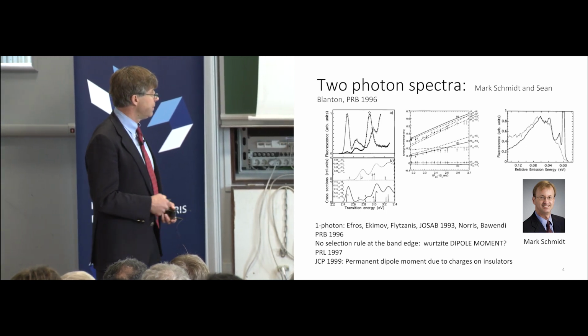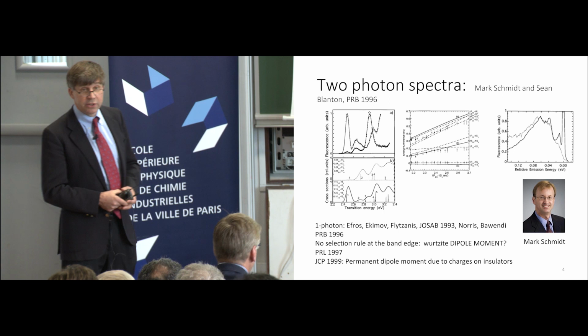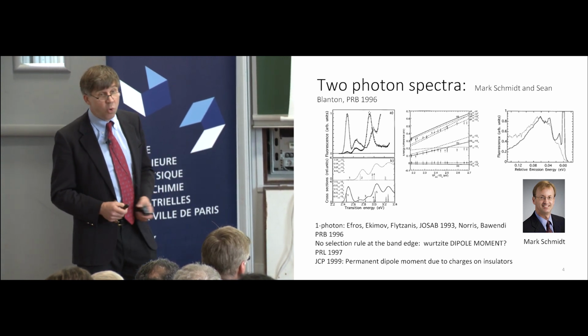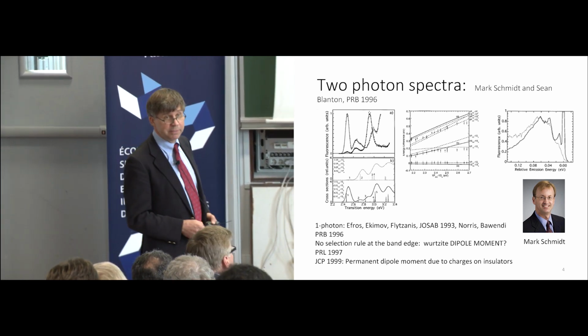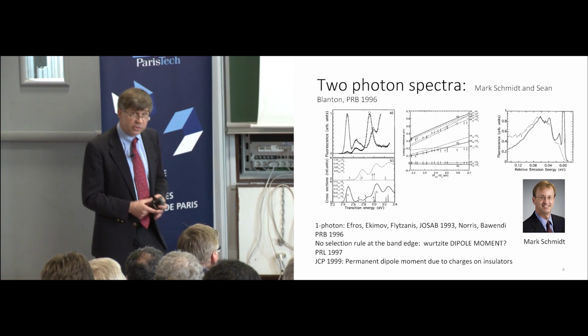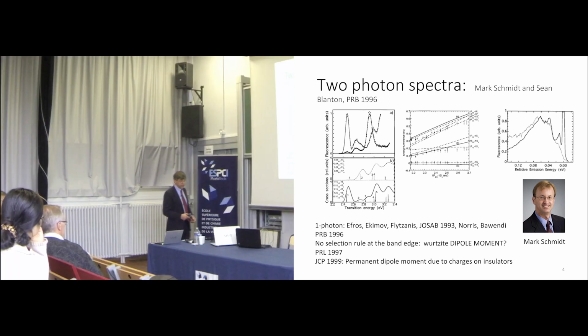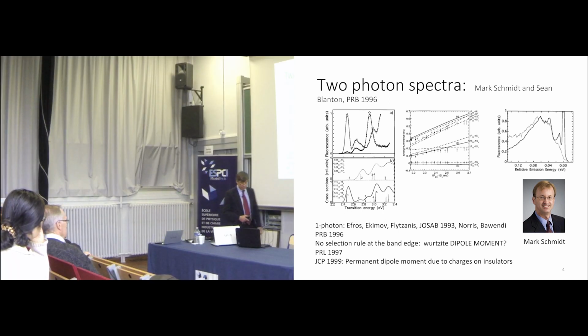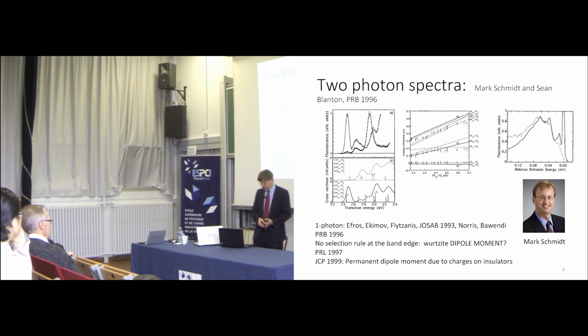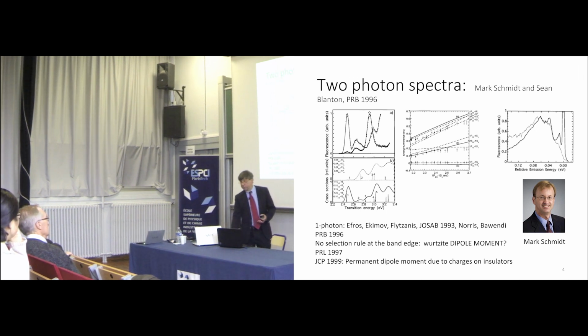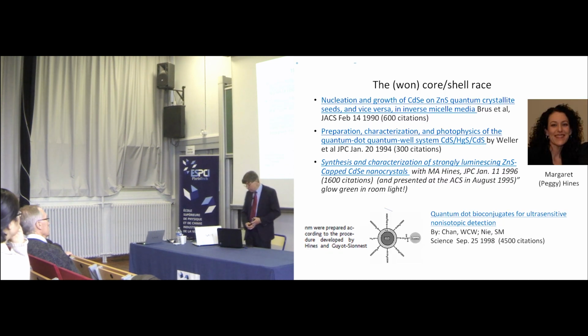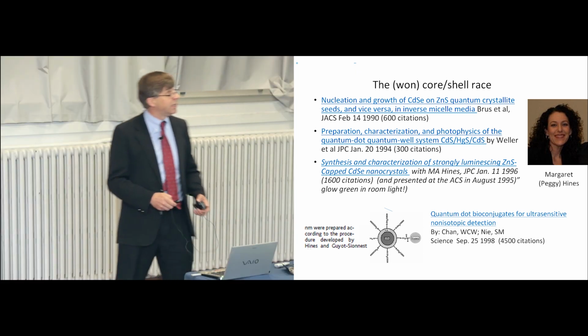Later on, Moonsub Shim made the same measurement on other particles, and we found that the dipole moment was always there as long as you look at an insulating particle. And that made us aware for the first time of the idea that charges are going to be decorating the surface of an insulator, and as a result, there will always be some effect of charges or dipoles. So this was the lost race. The one race we won, as Sasha very kindly reminded you, was the core shell.